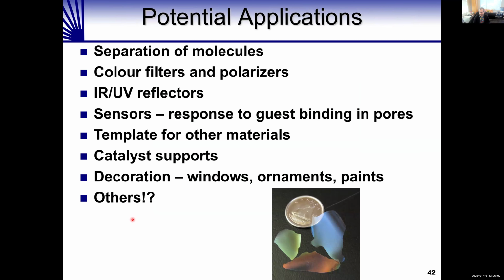Some of the potential applications of this material we're exploring include separation of molecules. Many molecules exist in a left-handed or right-handed form called enantiomers, and it turns out they travel at different rates through our material because our material has a left-handed helical twist. So we can use these silica films to separate these kinds of molecules, which are otherwise extremely difficult to separate.